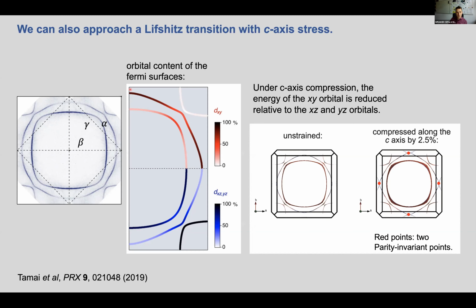This Fermi surface expands to both Van Hove points simultaneously. My colleague Helge Rosner calculated that this should happen at a c-axis compression of about 2.5%. We should reach both of these points at the same time. So if we have an even parity order parameter and we can access both of these points where the density of states is extremely high at the same time, then presumably we're going to see a really dramatic enhancement of Tc. Maybe we even get our longed for room temperature superconductor.